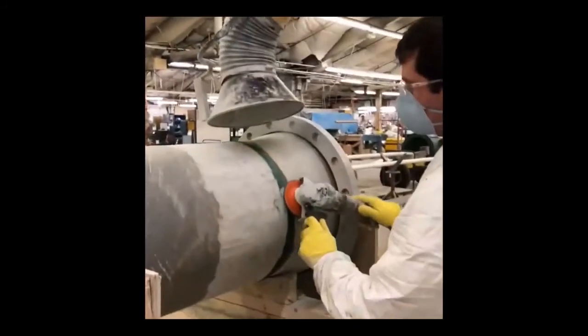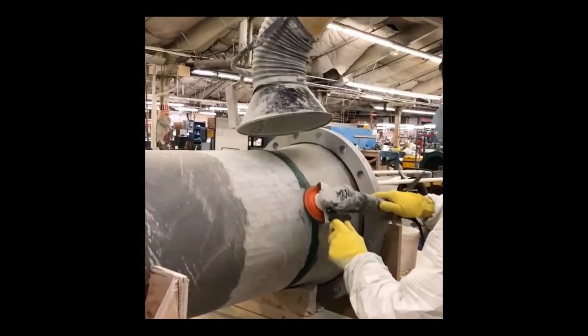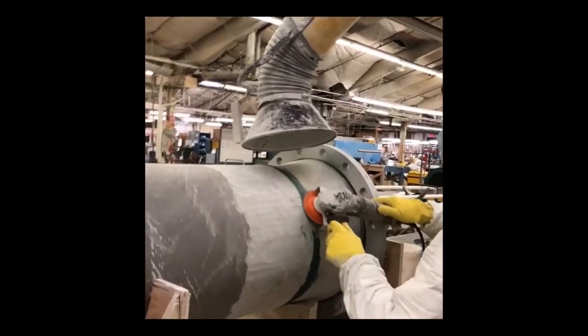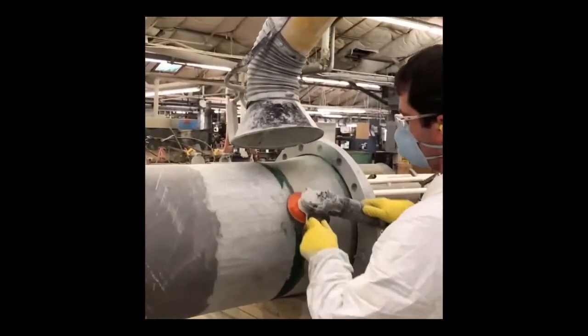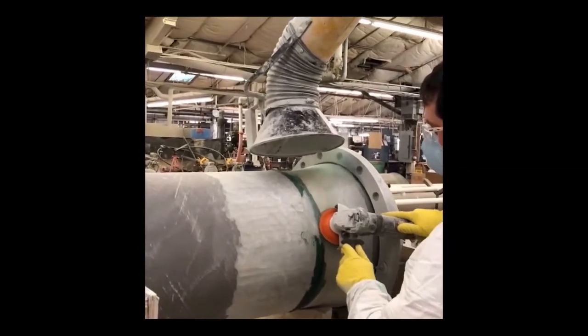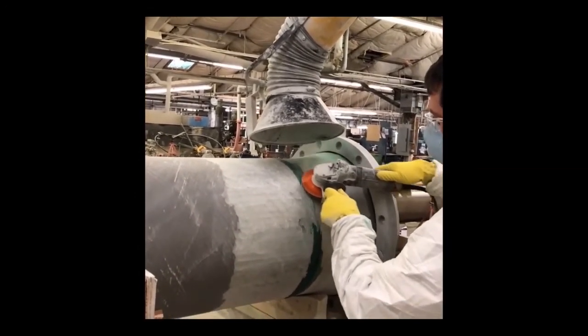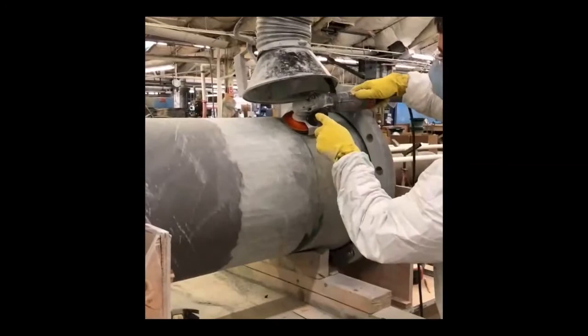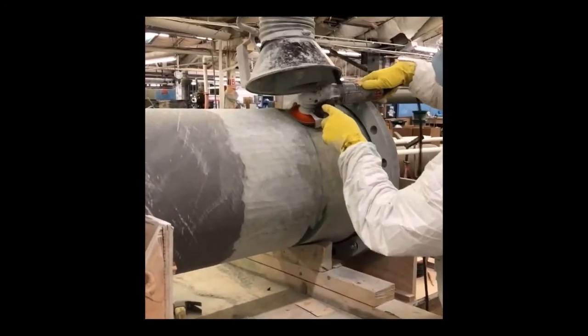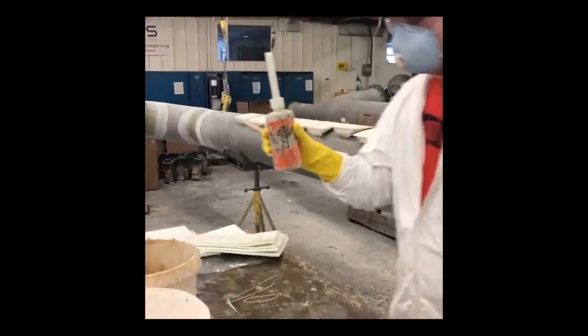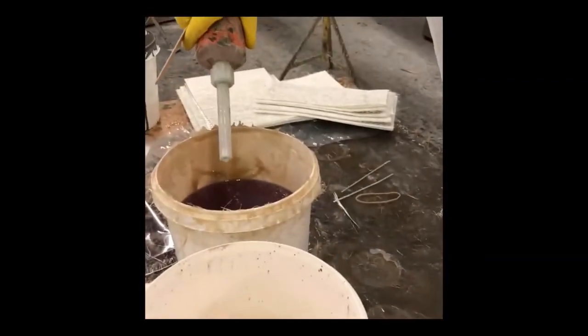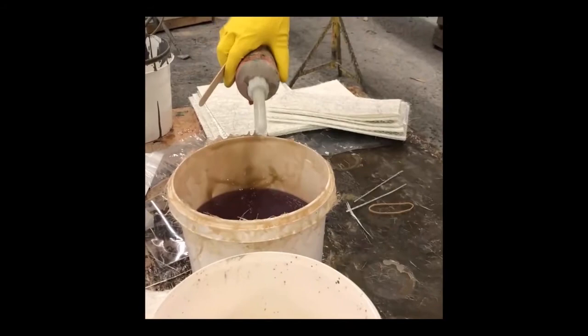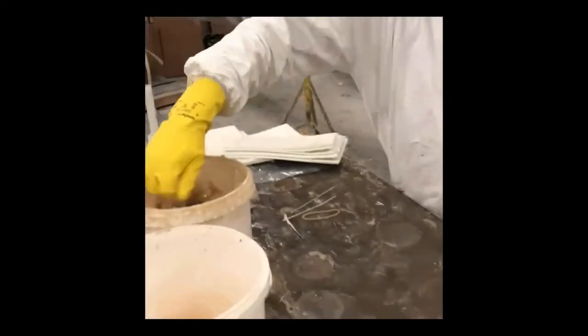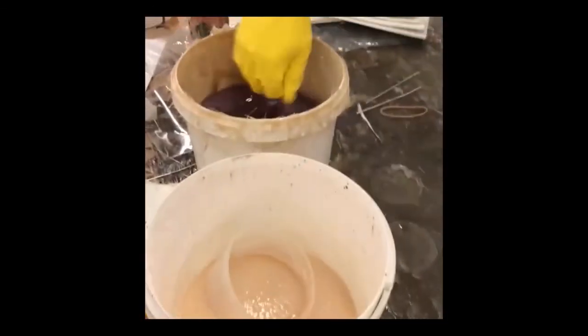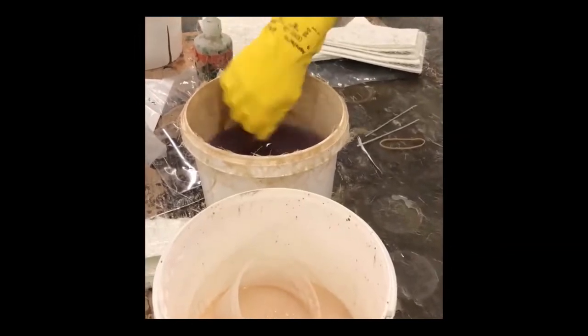Then what he's going to do is grind off the majority of that once it's cured. You can see here once he gets up to the top there, he's only going to have a thin line of crevice paste left and he's going to get a good bond when he goes to laminate over top of that. So the next thing the technician is doing is he's taking resin that's been promoted and he catalyzes the resin. He mixes it up well. And now what you're going to do is actually wet out the layup surface.